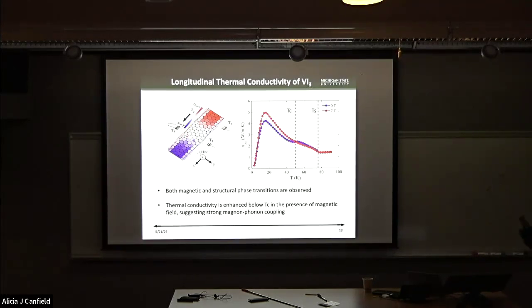Okay, so as I just mentioned, here we observe two anomalies associated with the structural phase transition and the magnetic phase transition. And furthermore, we found that in the presence of the 7 Tesla field, the thermal conductivity increases. As we just pointed out, this system is an insulating compound. Therefore, there are two dominating heat carriers. One is magnon and the other is phonon, right? And these two quasi-particles could scatter each other. At zero field, the phonons are scattered by the magnons, which is going to lead to the suppression of the thermal conductivity.